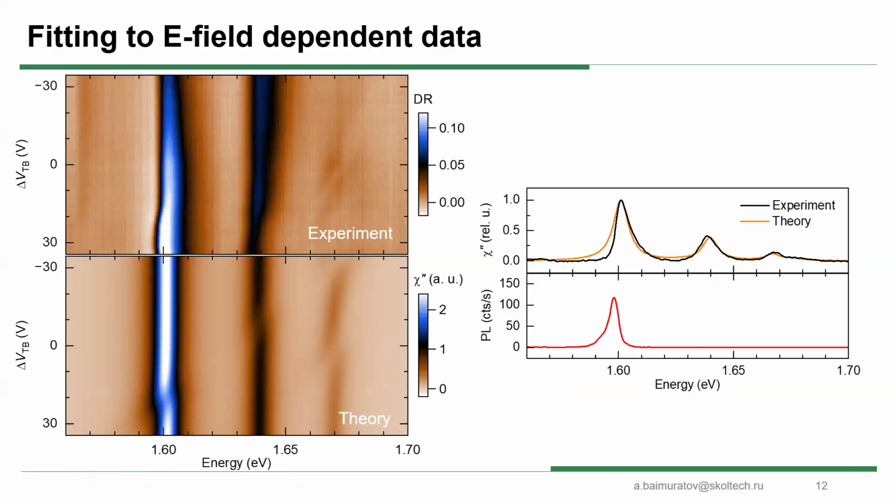As I said, we took a potential for the exciton, and by fitting the parameters of this potential to data from experiment, we found that we have 3 excitonic peaks. These are absorption from experiment and from theory. At least the first 2 absorb strongly enough to see them in the system, and we have a 3rd peak. We call them M1, M2, and M3.